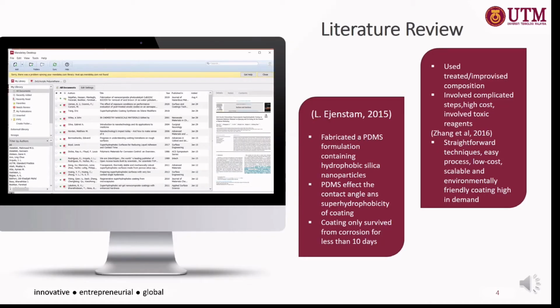So now you may ask, why did I choose to carry out this project and what are the gaps of this research? L. Ejenstam, 2015 did fabricate a polydimethylsiloxane formulation containing hydrophobic silica nanoparticles with different addition of PDMS percentage, but the coating was not stable over a long time. With the presence of too much PDMS, the contact angle and superhydrophobicity of the coating are affected. Corrosion resistance of this coating only managed to survive less than 10 days, then the coating would crack under corrosive immersion, 3% NaCl water solution.